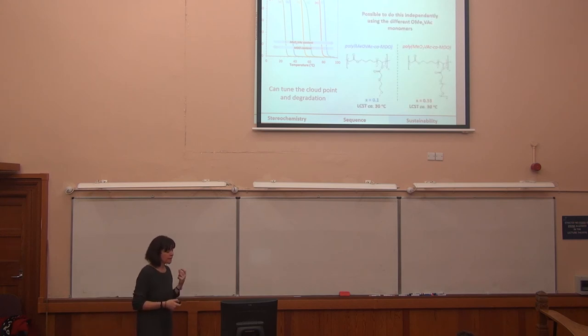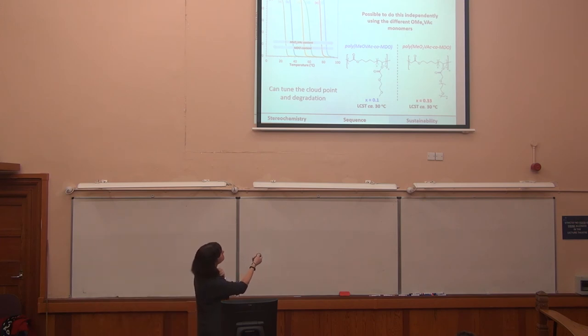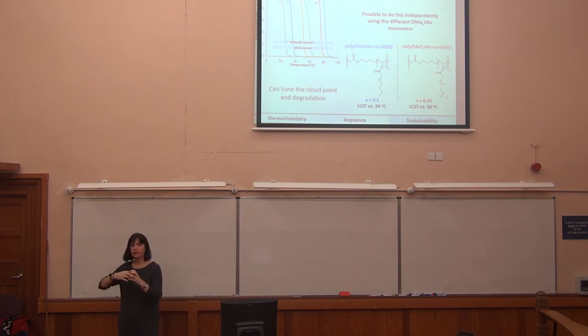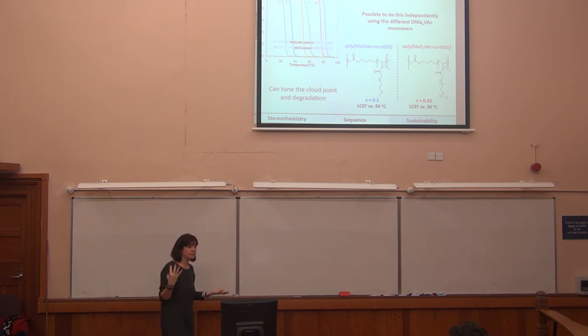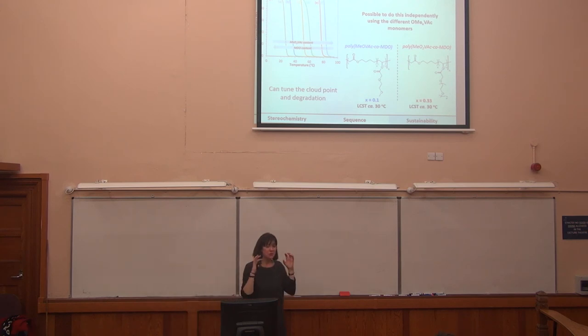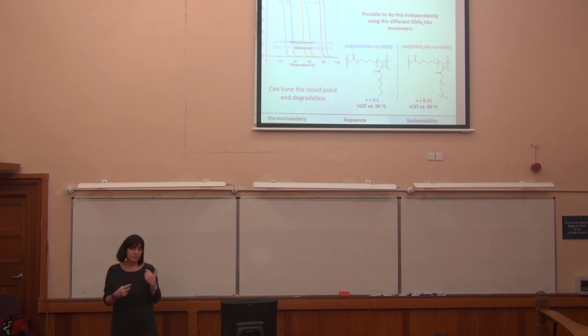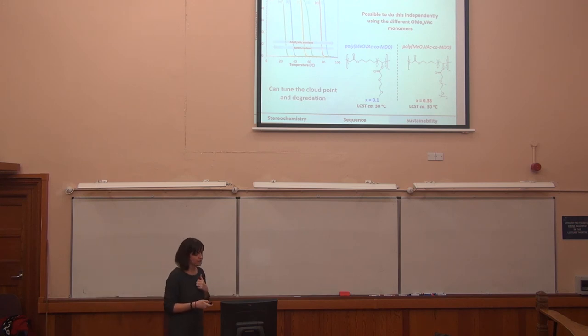The other thing that we were quite interested in: these are two polymers that would respond at the same temperature, so would release their payload at the same temperature, but they have significantly different amounts of degradable monomer in there. So we can actually start to independently tune response temperature from rate of degradation, which you actually can't normally do, because they're often so closely interlinked, but because of the design of our system, we can actually now start to do it.